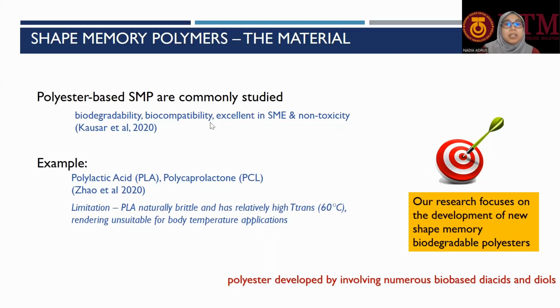So polyester-based shape memory polymers are commonly studied because they are biodegradable, biocompatible, excellent in shape memory effect, and also non-toxic. Examples are PLA, which is polylactic acid, and PCL, which is polycaprolactone. However, PLA is naturally brittle and also has a relatively high transition temperature above 60 degrees Celsius. Hence, it is not suitable for body temperature applications. Therefore, our research focuses on the development of new shape memory biodegradable polyesters by involving numerous bio-based diacids and diols.